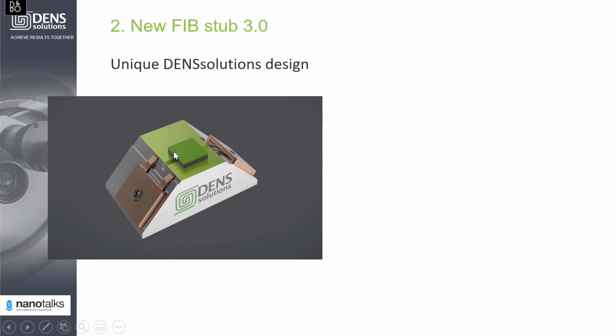We also have two sides at 45 degrees. On those sides, we can put chips, nanochips. This FIB stub is compatible with all double tilt chips for heating, for biasing, or heating and biasing. On top of that, it can also be used with single tilt heating chips. The FIB stub is compatible with Thermo Fisher or FEI and JEOL FIBs, and the rest of the FIBs are still to come.